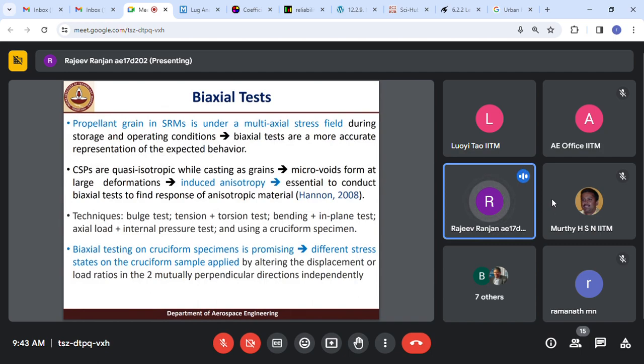We conducted biaxial tests, and there are two reasons behind the motivation. First, the propellant grain in solid rocket motors is subjected to a multi-axial stress field, so conducting biaxial tests will be a more accurate representation of the expected behavior. Secondly, composite solid propellants, when cast as grain in solid rocket motors, are quasi-isotropic in nature. However, upon loading, micro voids form in them, and they become anisotropic. And biaxial testing is essential to characterize anisotropic material. So these two reasons are necessary. Due to these two reasons, we conducted the biaxial test on composite solid propellants.